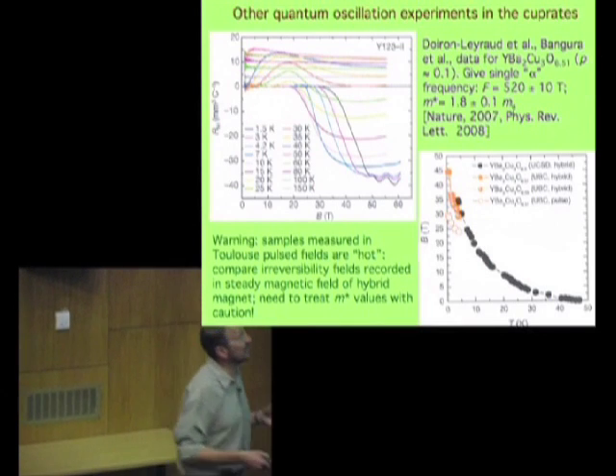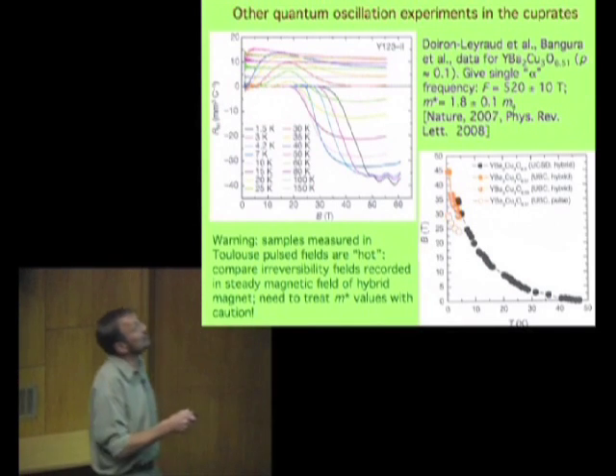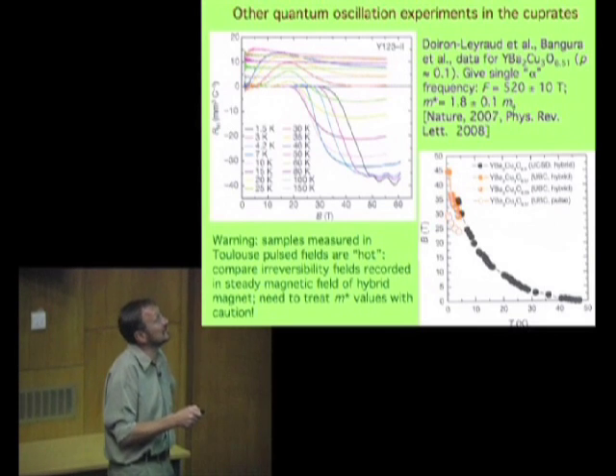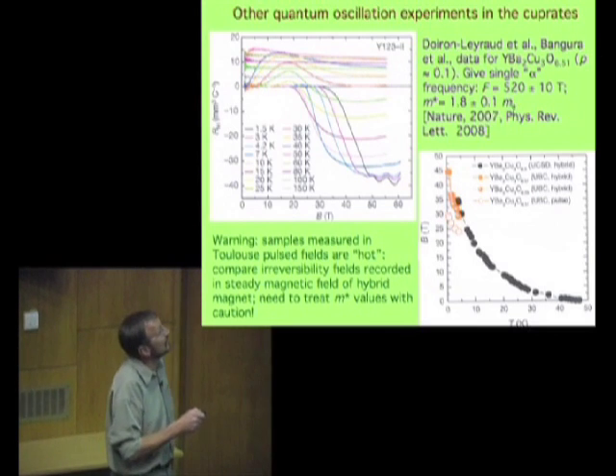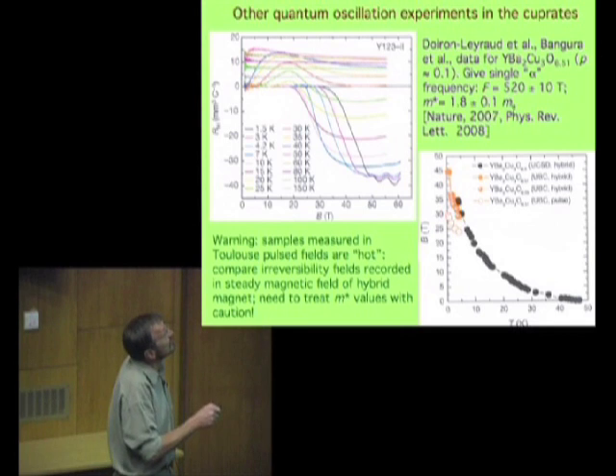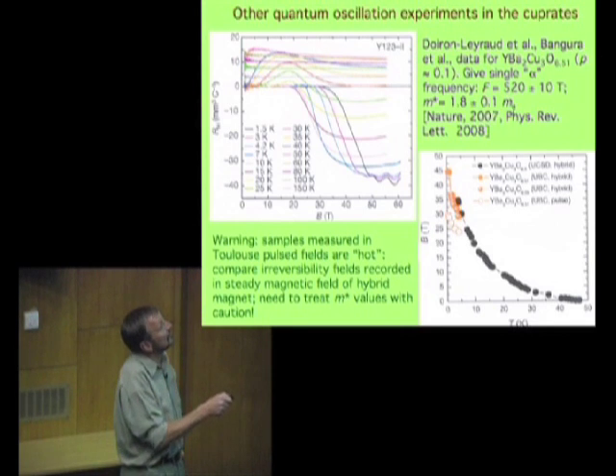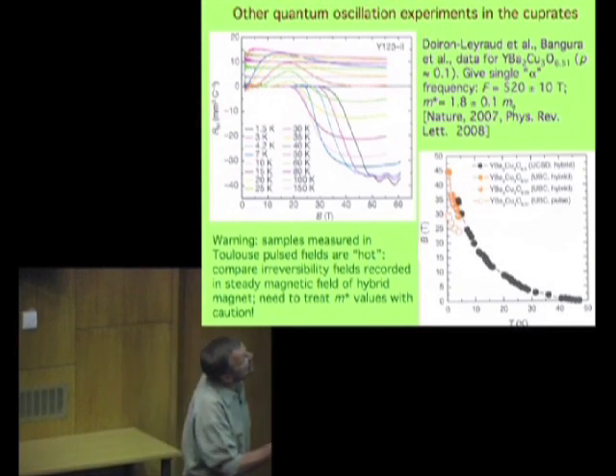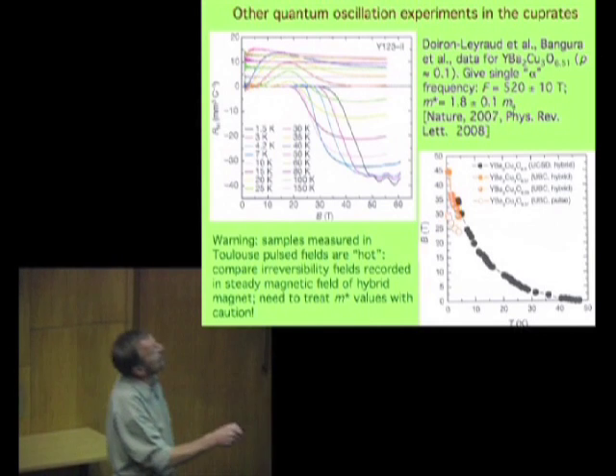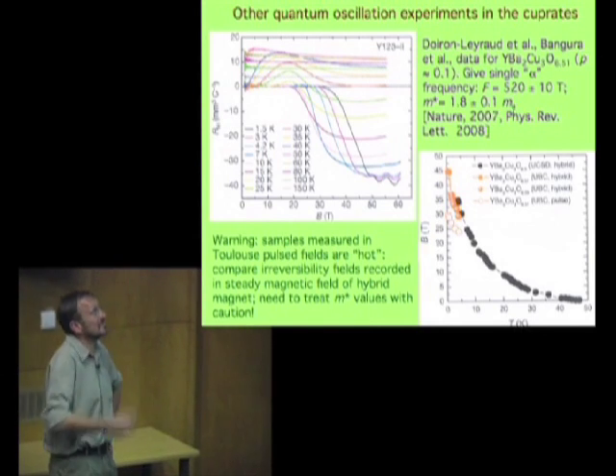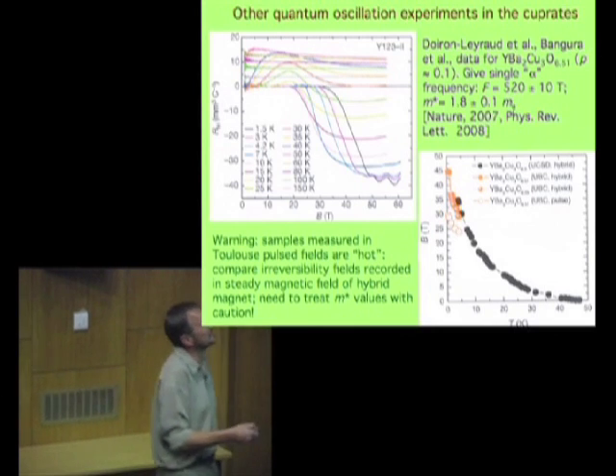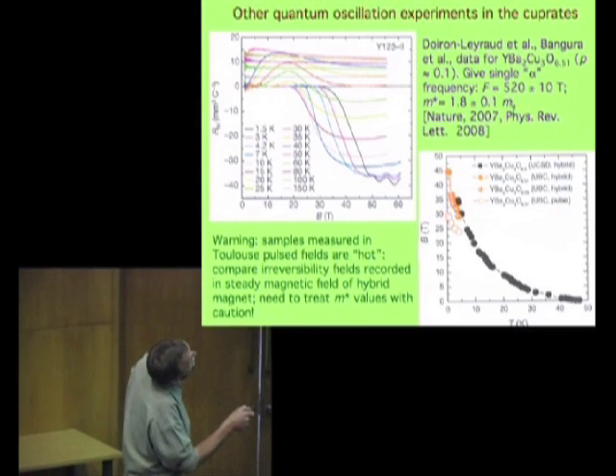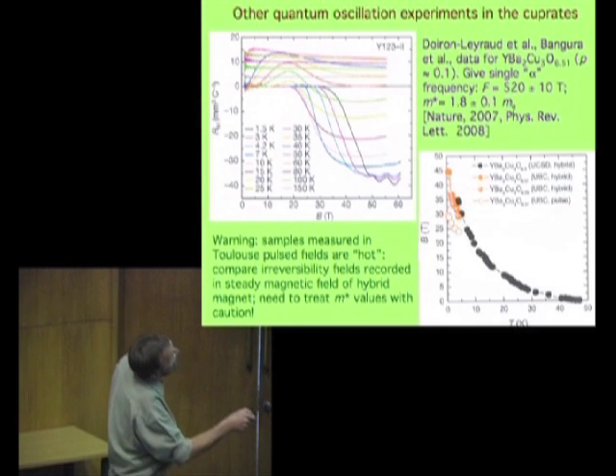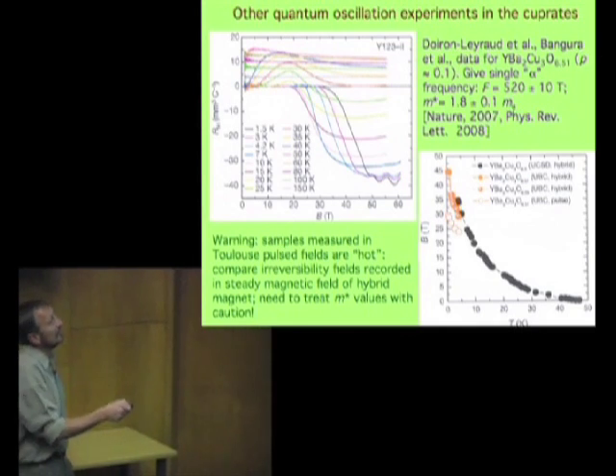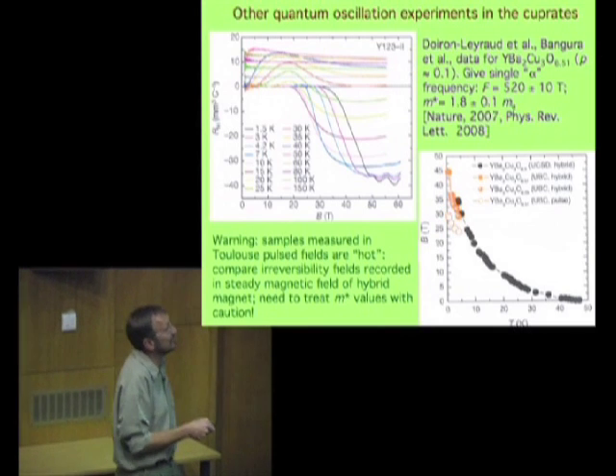Now, while this is going on, there are other measurements being made of quantum oscillations in the cuprates. These are some done in Toulouse by a former student of mine. This is the Hall conductivity of a different cuprate, but still it's a 2-dimensional hole-doped superconductor. You can see once the Hall effect gets through the upper critical field of superconductivity, we again see these oscillations here. Slightly lower fields because this thing has a lower critical field.